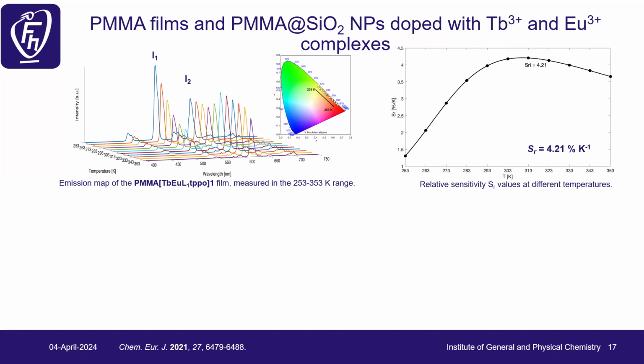And here we got at 313, almost 4.2% per Kelvin. So it's the same, 4.2% per Kelvin or 4.2% per degree. We can see the change of temperature, which is interesting. And it's just in a short temperature range from -20 to +80 degrees. But by changing the ratios, we can play in a different temperature region. So the purpose can be changed just by slightly adding or changing the concentrations or ratios of terbium and europium.